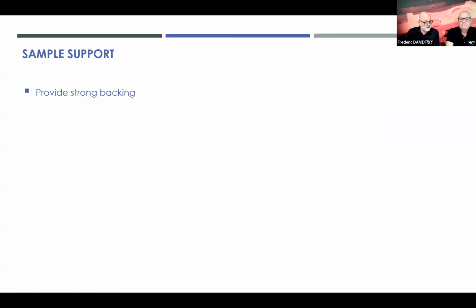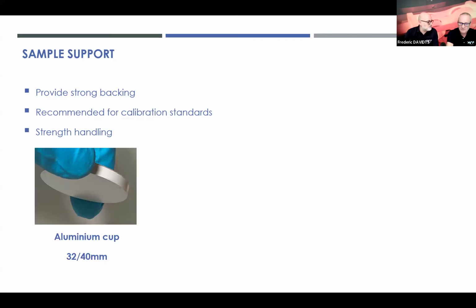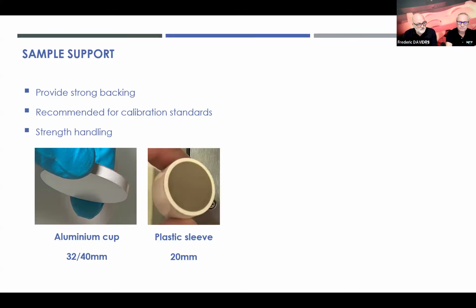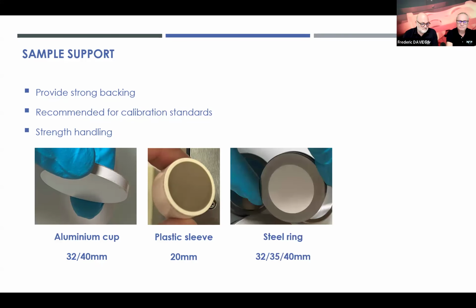Then the sample supports. They are there to provide a strong backing. This is mainly recommended for all applications, but of course more for calibration standards if you want to keep them a longer time and reuse them after. So it of course reinforces strength and handling, and for that the most used are the aluminum cups. They are available in 32 or 40 millimeter, and you can have them in different forms and shapes, conical or straight. We call them tapered for the conical and straight. We have also the plastic sleeve, so it's a little bit, I would say, not common, but it works also very well. The steel rings are also available in different dimensions, 32, 35, 40 millimeter.